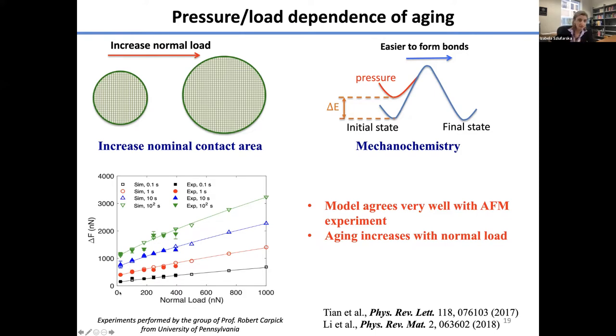So this is a frictional sliding on that vertical axis. This is normal load. The different curves correspond to different aging times, so you can ignore, just pick one of them. And you can see that the higher the load, the more aging we have, okay? And you can also see that the solid points are experimental points. The open symbols are our simulations. So we have a model that can accurately capture the pressure effects on aging, at least in a single asperity.